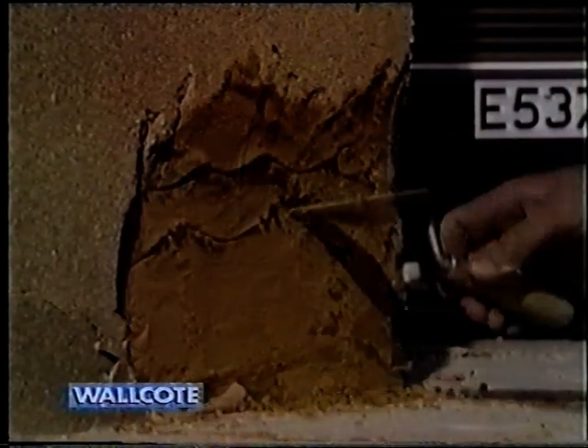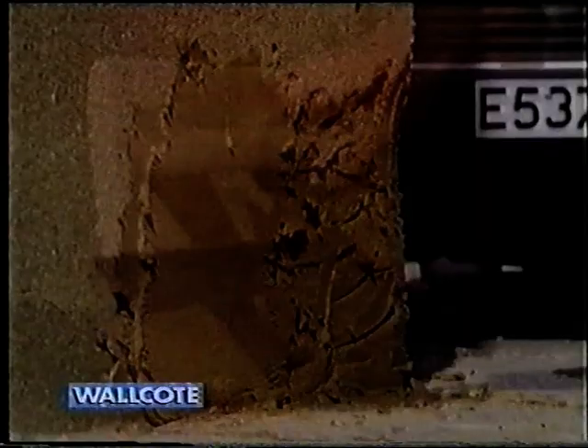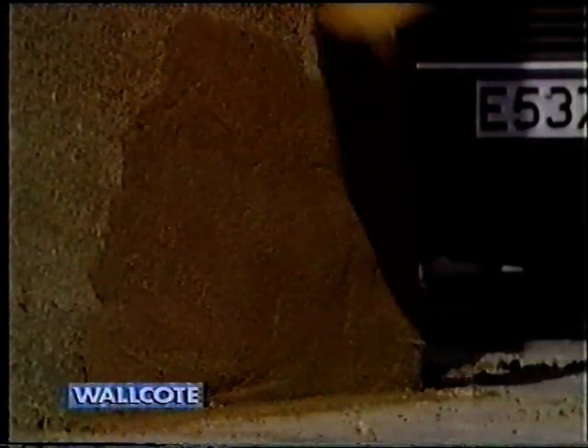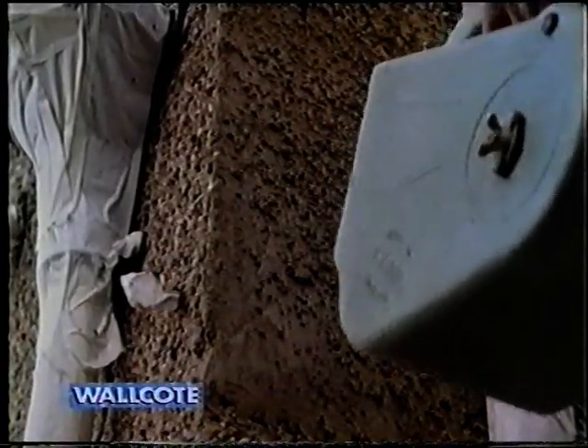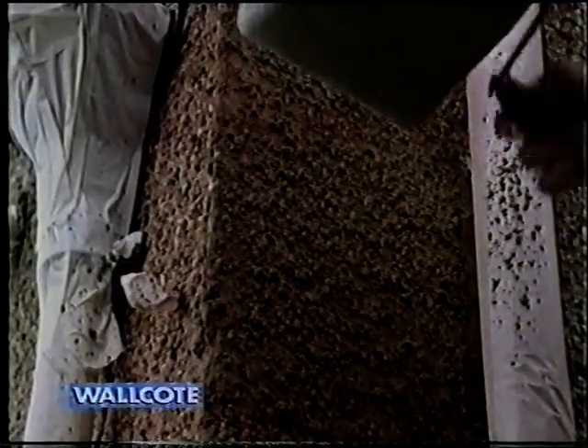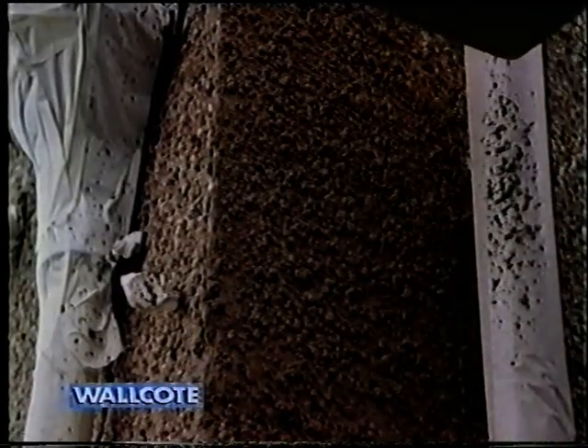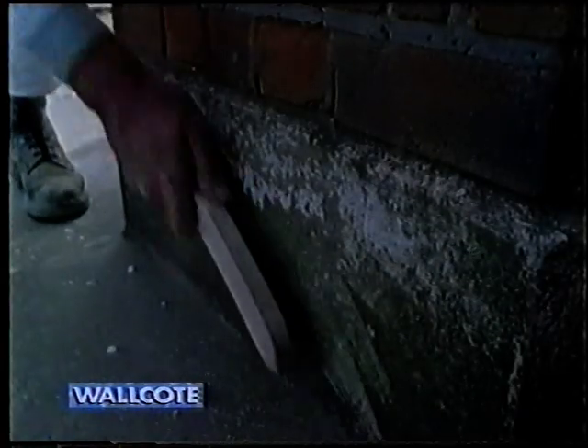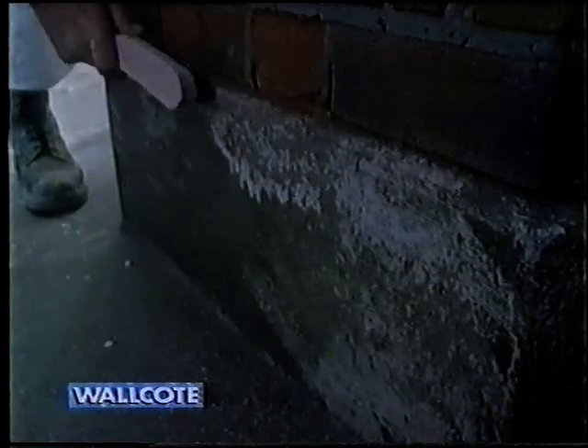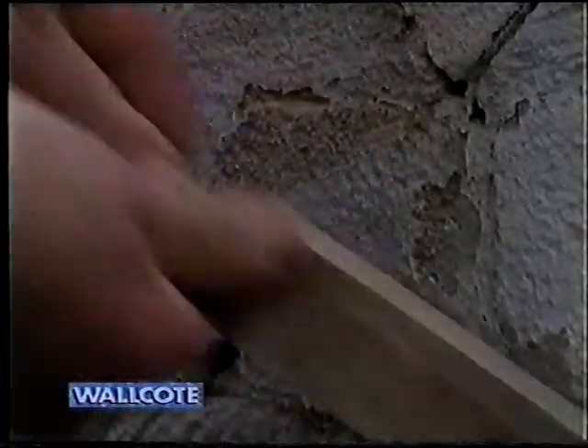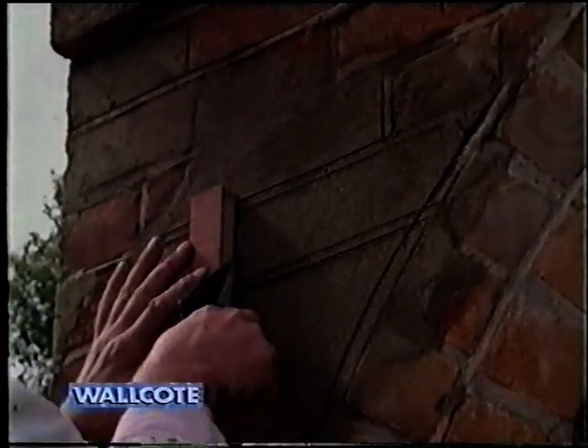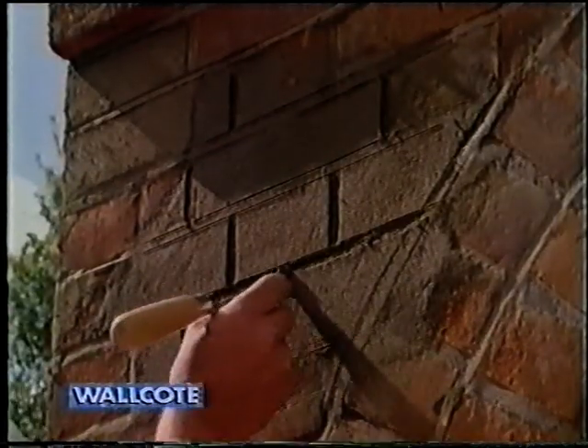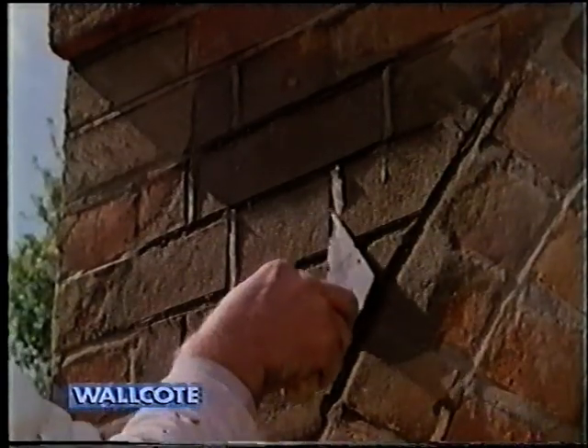Previously rendered areas which have been cut back are once again treated with the bonding primer and restored with 2 layers of a sand-cement mixture. Pebble dash finishes are matched by spraying similar-sized grit into the still wet surface with what's called a Tyrolean gun. Once the repair work has been carried out, cleaning down can begin. This involves wire brushing the grime and pollution, moss and algae from all surfaces. Scraping and wire brushing flaking paint from areas to be coated. Where brickwork is damaged, surfaces are recreated using a sand, cement and adhesive mix. Damaged pointing is raked out and replaced.